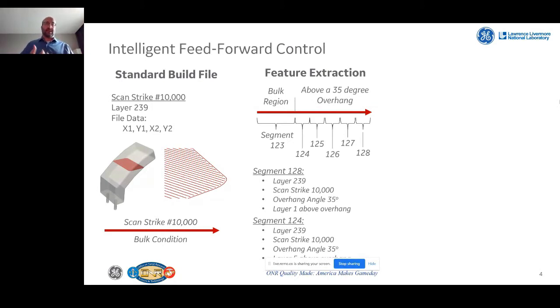For essentially looking at a laser strike during the processing of this part, trying to identify where we start approaching that overhang region. With segment 123 shown in the center of this slide, it's kind of the bulk region of the part. But then as the laser strike is going closer and closer to the edge of the part, towards that overhang section, we start identifying that it goes towards that very far edge, where essentially 128 is earmarked as the first layer above an overhang. 127 is the second layer above that overhang.